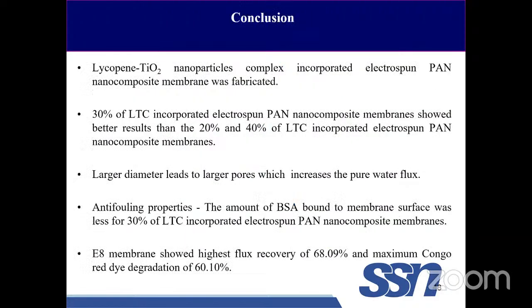So from this result, we conclude that lycopene TiO2 nanoparticles were successfully prepared by incorporating them in PAN nanofibers as a photocatalytic membrane, and 30% LTC gave us better results compared to 20 and 40, right? In connection to the anti-fouling property, BSA, the bovine serum albumin that we utilized as a protein foulant for measuring the choking of the fibers, gave us lesser choking in 30% LTC because these are uniformly distributed, and it avoids the clogging of proteins in the fibers. And we have achieved a dye degradation of about 60%, and the flux recovery ratio is about 68%. And the degraded products were biphenyl, naphthalene, and phenol.